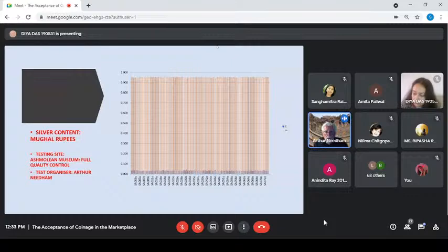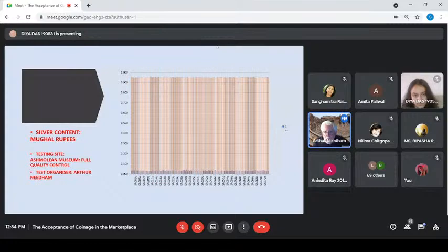And this is a series of coins that were tested across a number of mints. And basically it says the silver was about 95%. And have a look at how straight that line is. And we're talking about coins made basically 450 years ago. So all across the subcontinent, from Afghanistan almost to the bay, they minted coins at 95.5%, give or take, silver. So this goes back to the fact I was saying, it could be tested, it could be shown, and there is just one set of proof over many thousands of coins tested. Next slide, please.